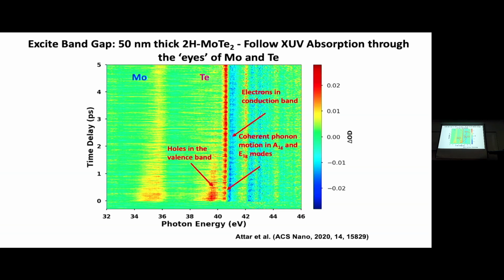So if I see the molybdenum, it comes at around 35 electron volts, and time is going up here. And initially, it's very broad. And if you follow it, it gets narrow. And so this is the holes in the molybdenum, showing through the molybdenum in the valence band, and they're born hot, which is why it's so broad, and then they narrow up as it's cooling. And we see the same effect in the tellurium, that it's born hot here, and it's cooling.